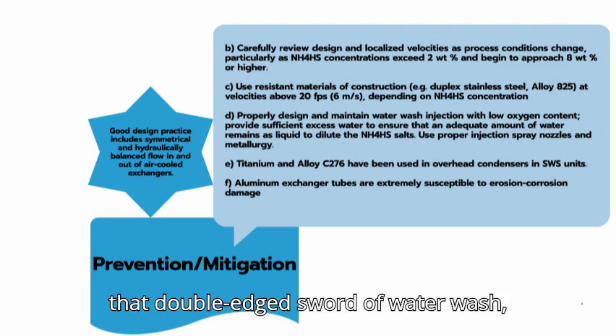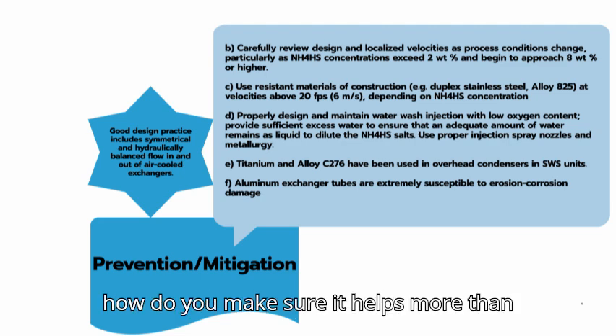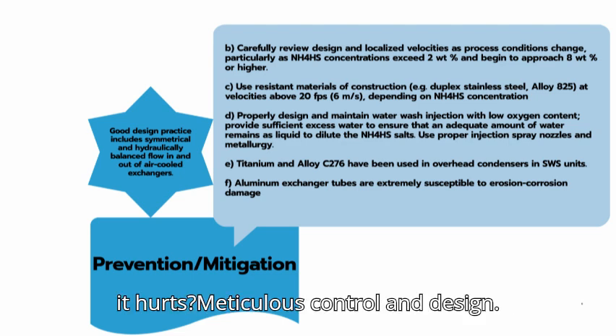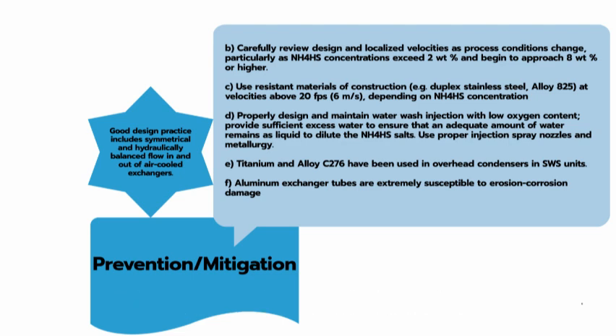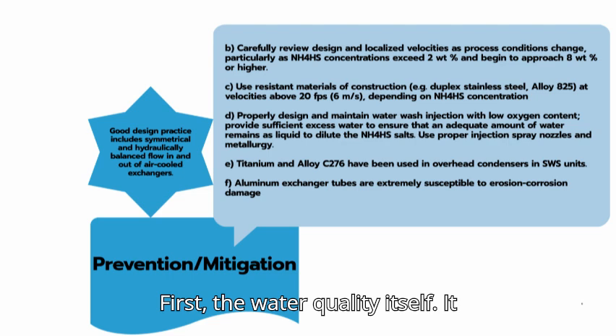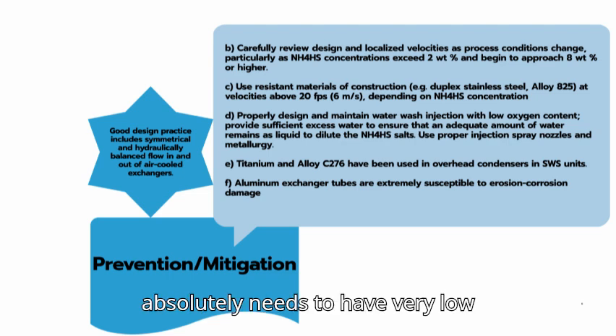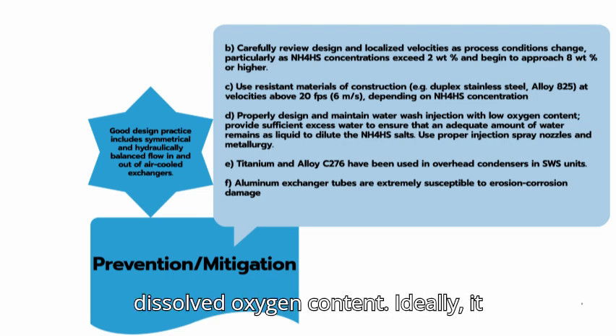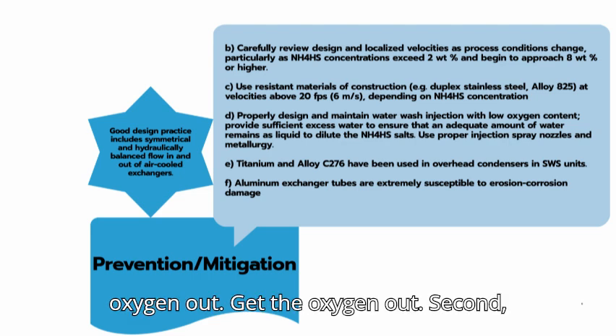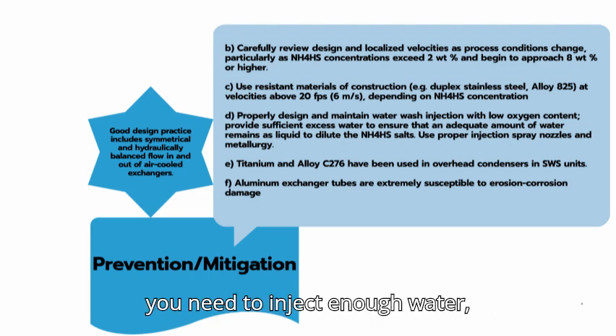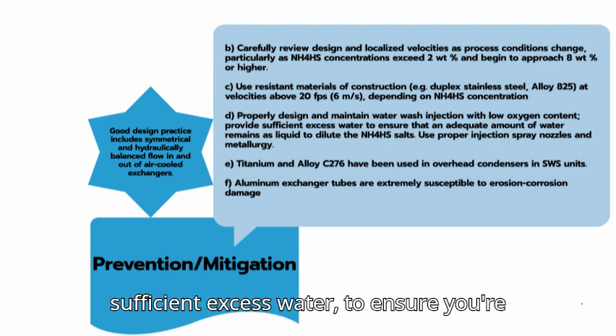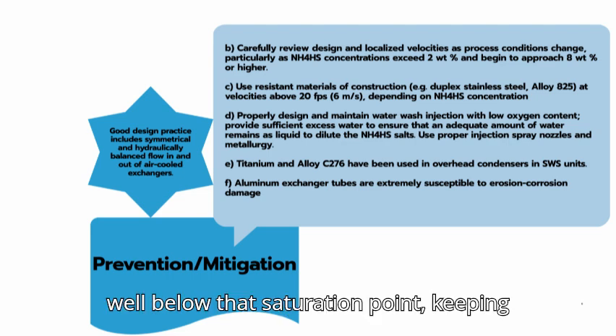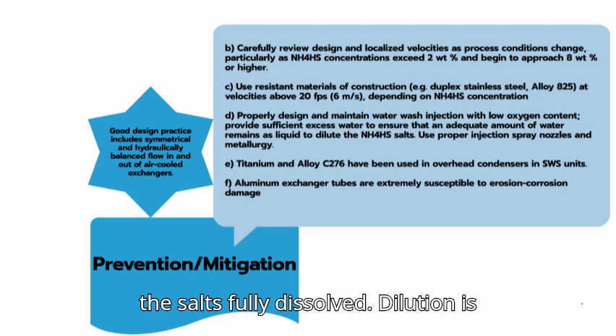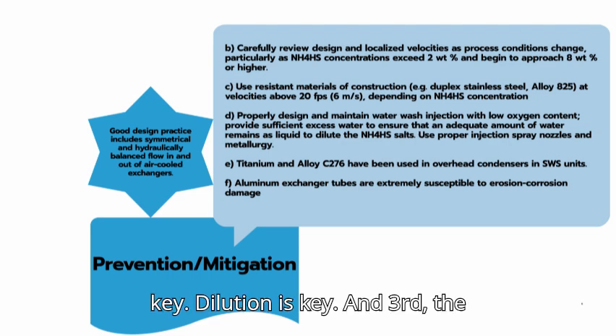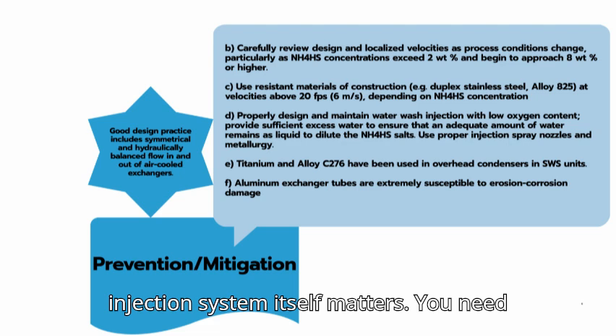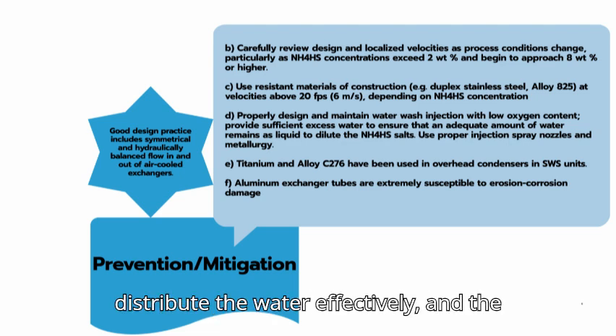Right. And managing that double-edged sort of water wash, how do you make sure it helps more than it hurts? Meticulous control and design. First, the water quality itself. It absolutely needs to have very low dissolved oxygen content. Ideally, it should be deaerated water. Get the oxygen out. Second, you need to inject enough water, sufficient excess water, to ensure you're well below that saturation point, keeping the salts fully dissolved. Dilution is key. And third, the injection system itself matters. You need properly designed spray nozzles to distribute the water effectively.